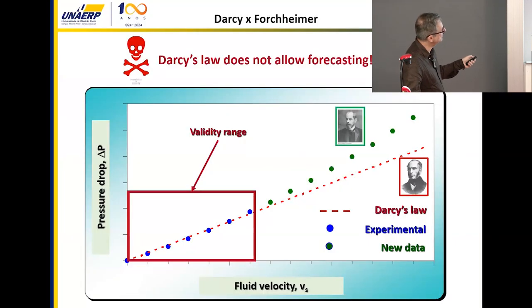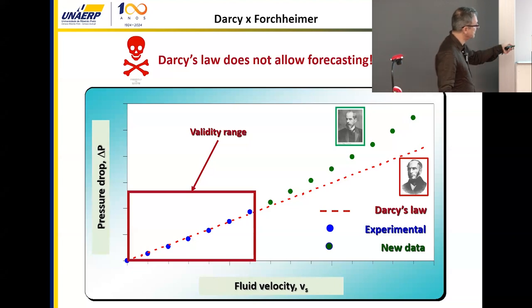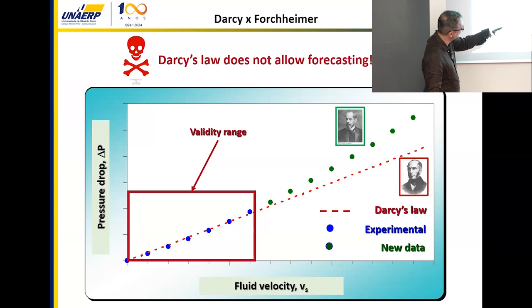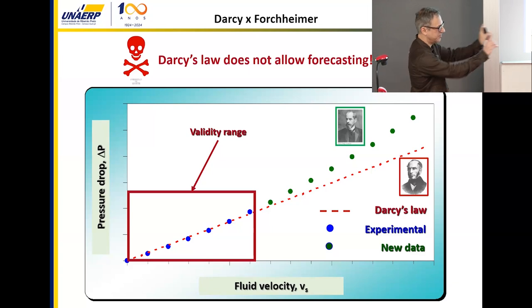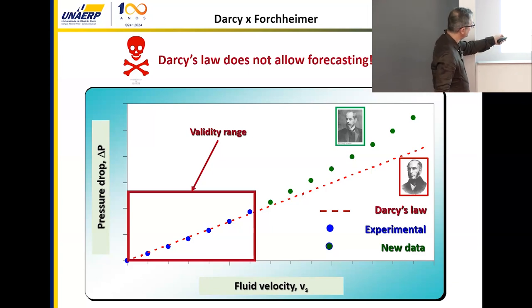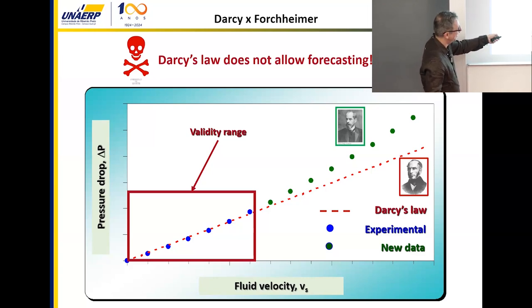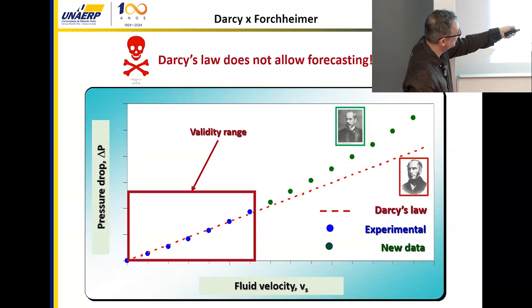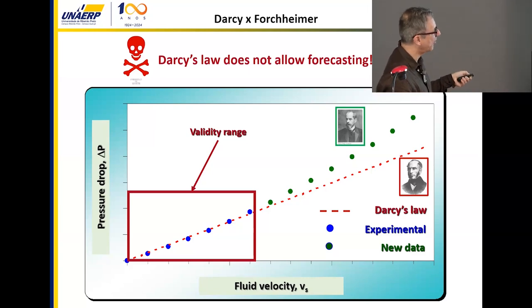So the point of Darcy's law is that it does not allow for forecasting. For example, in the lab, I will show you very soon, if you take the experimental points for a region, then you can use this information only in the region where you did the data collection. If you try to do the forecasting, this red line is the Darcy's law, this is the slope of the equation. The point is that you cannot predict the behavior anymore. So in our case, we don't use Darcy's law just because of that. If you measure in a range, you cannot extrapolate that for other ranges. You lose the reliability of the data.